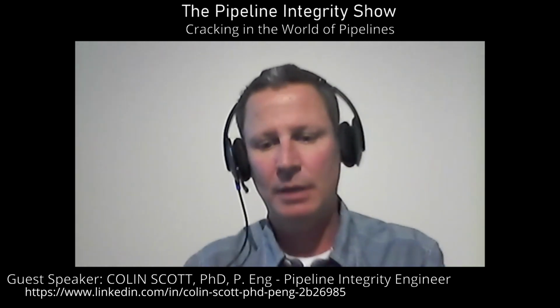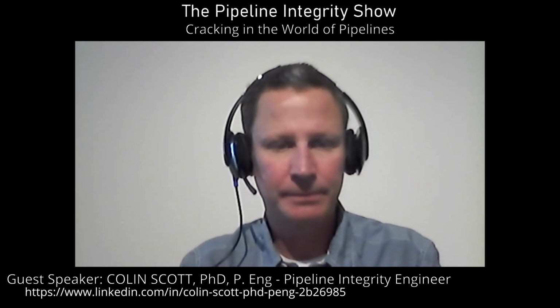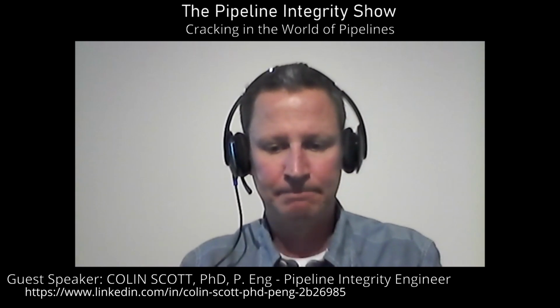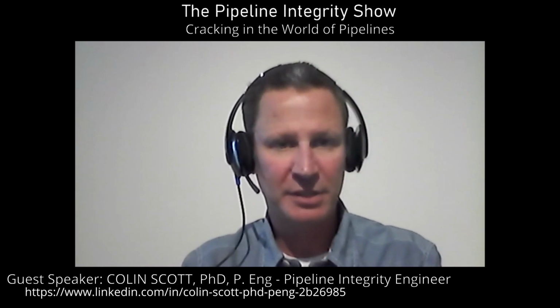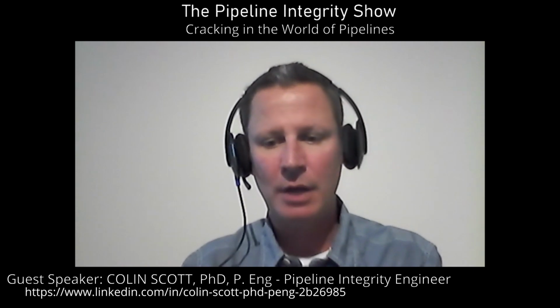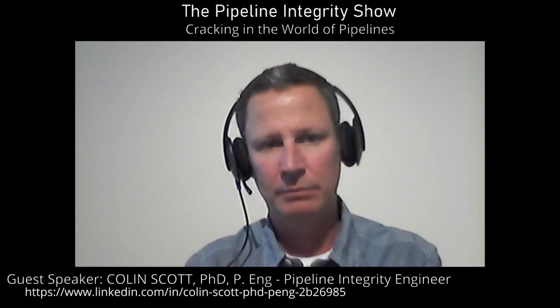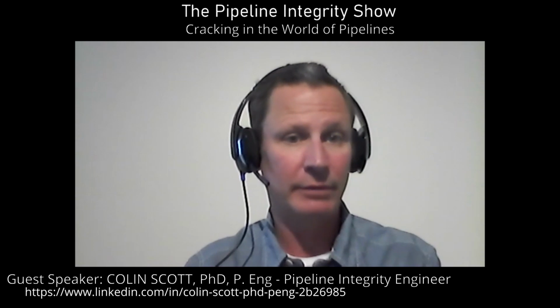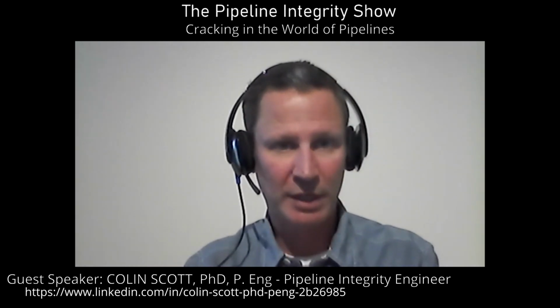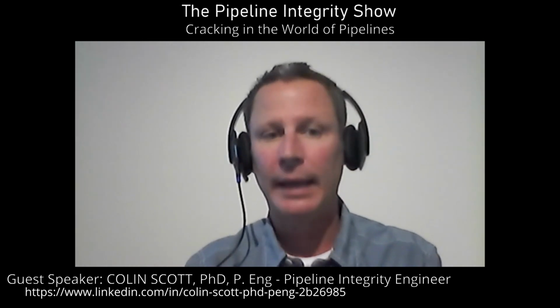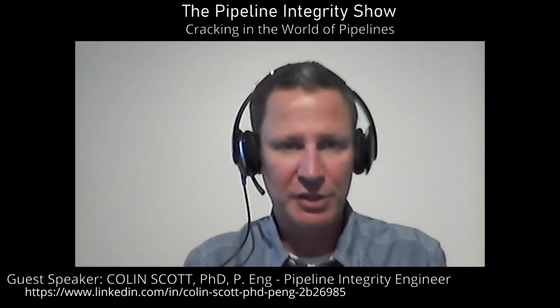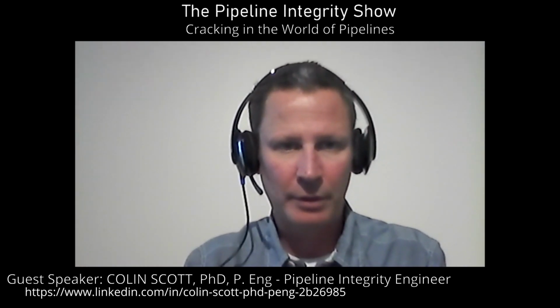This is the $64,000 question. Toughness tends to be a very, very tricky thing to measure. One of the key things that makes it tricky is that a lot of the time we're worried about the toughness of the long seam weld, and the long seam weld is by definition going to be weaker if you have a lot of defects in it, or if you didn't do a good normalization program during the weld. So toughness is one of the challenges that we fracture mechanics people work with all the time.